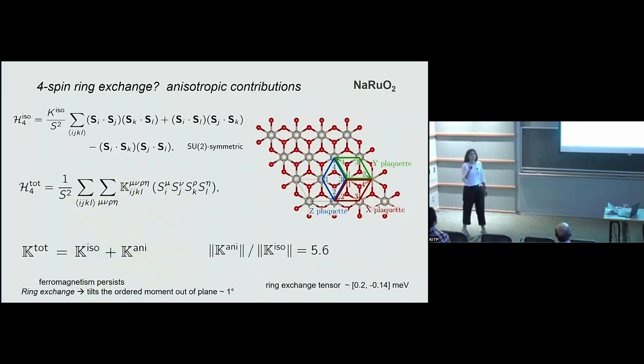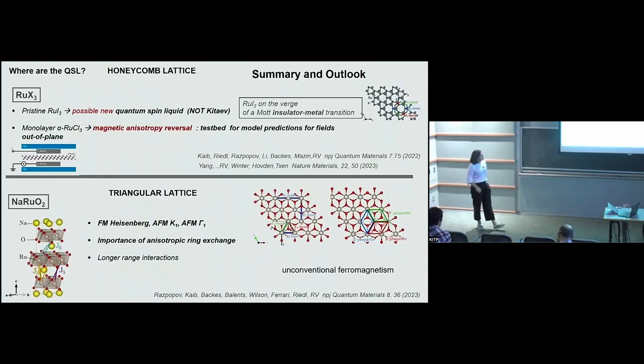However, because we have here a bond-dependent triangular lattice, we not only have contributions coming from the symmetric SU(2) symmetric ring exchange, but there are also contributions coming from anisotropic ring exchange. And this is very interesting because these contributions are responsible for predicting that the ferromagnetism will tilt. So with that, I come to my conclusions.